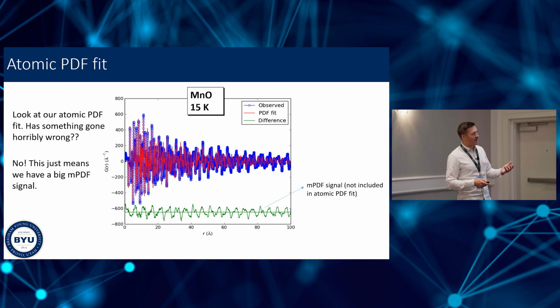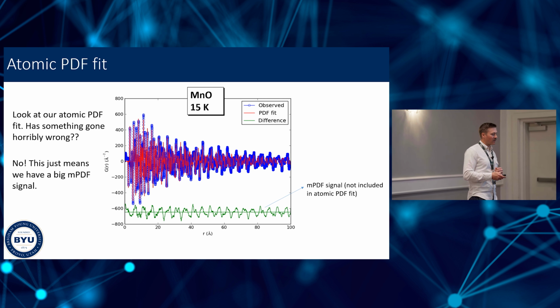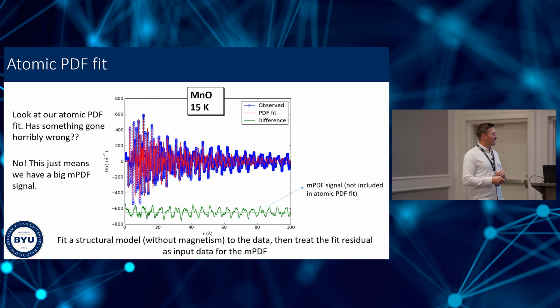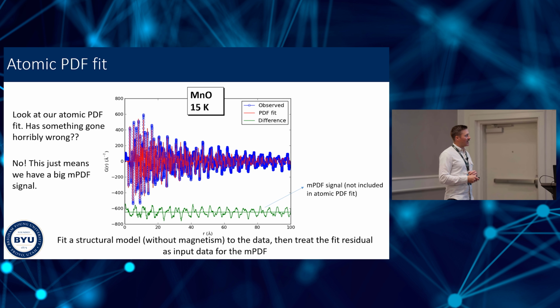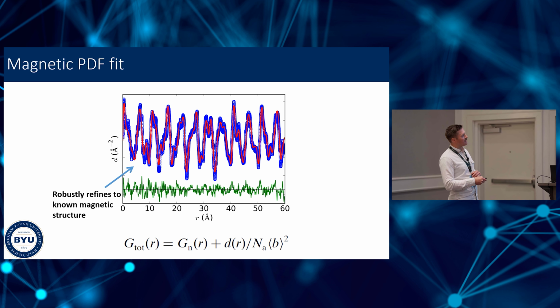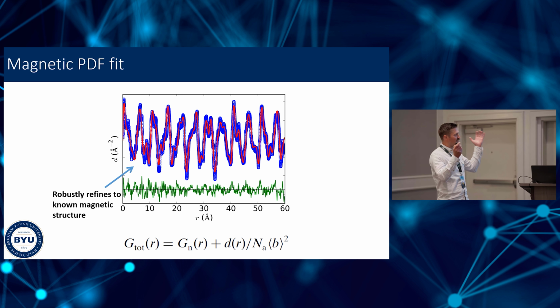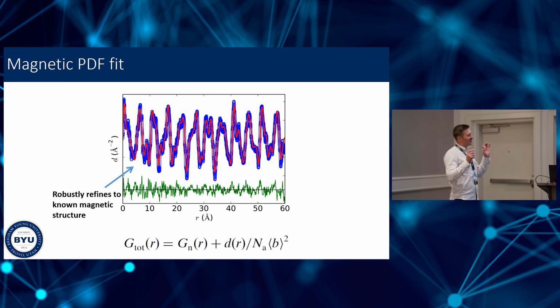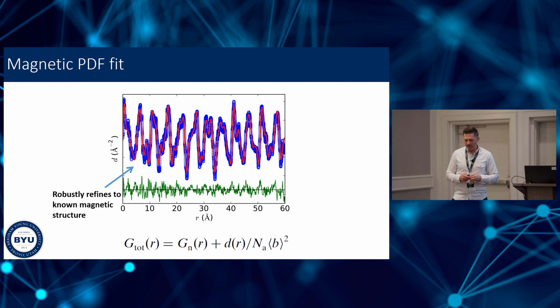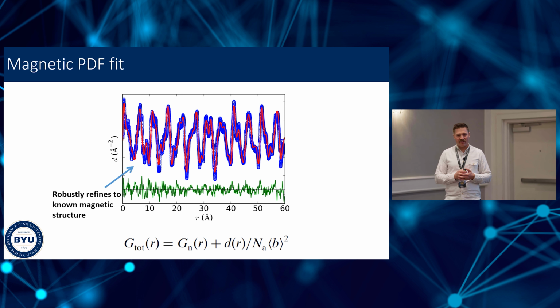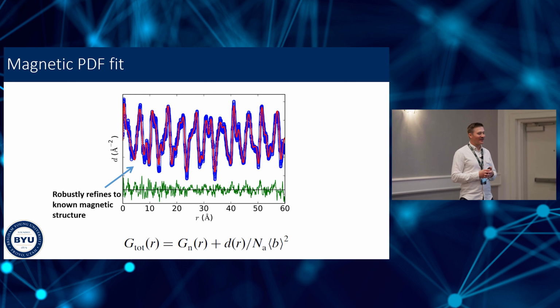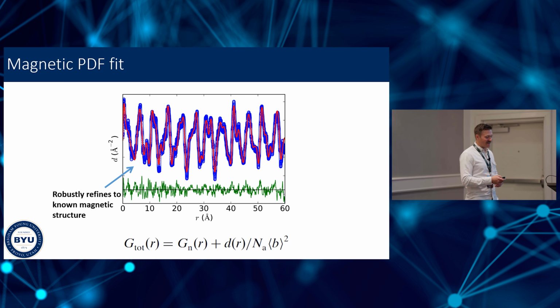And we have an expression for the magnetic PDF. And we know the low temperature magnetic structure of manganese oxide, so we can just calculate the magnetic PDF, and it fits perfectly. So here we are zooming into that fit residual, and the red curve here is the magnetic PDF. So this was the first magnetic PDF fit. It worked. It was a huge relief that I didn't make any mistakes in the math. Now, it wasn't very groundbreaking to determine the low temperature magnetic structure of manganese oxide, because that had been known for 60-something years.